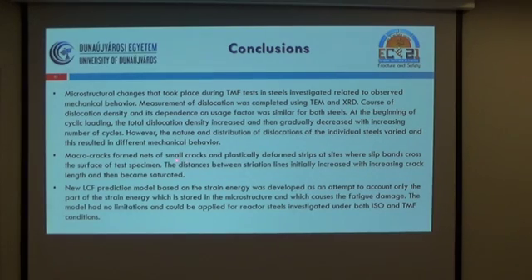Macro cracks form nets on the small cracks and plastically deformed strips at sites where the slip bands cross the surface of the test specimens. The distances between the striation lines initially increased with an increase in crack lengths and then became saturated. You remember this small picture in the corner. And an energy-based low cycle fatigue prediction model based on strain energy was developed as an attempt to account only for the part of the strain energy which is stored in the microstructure and which causes the fatigue damage.